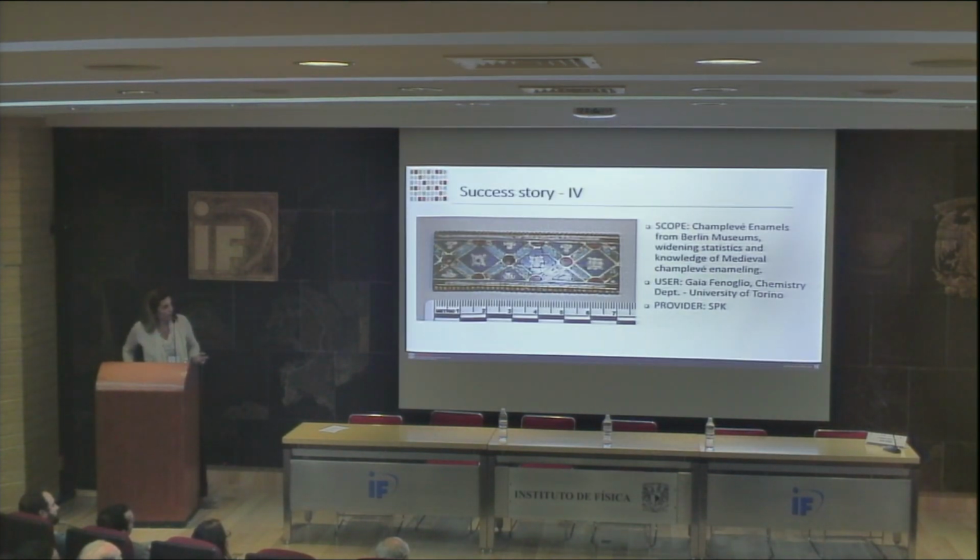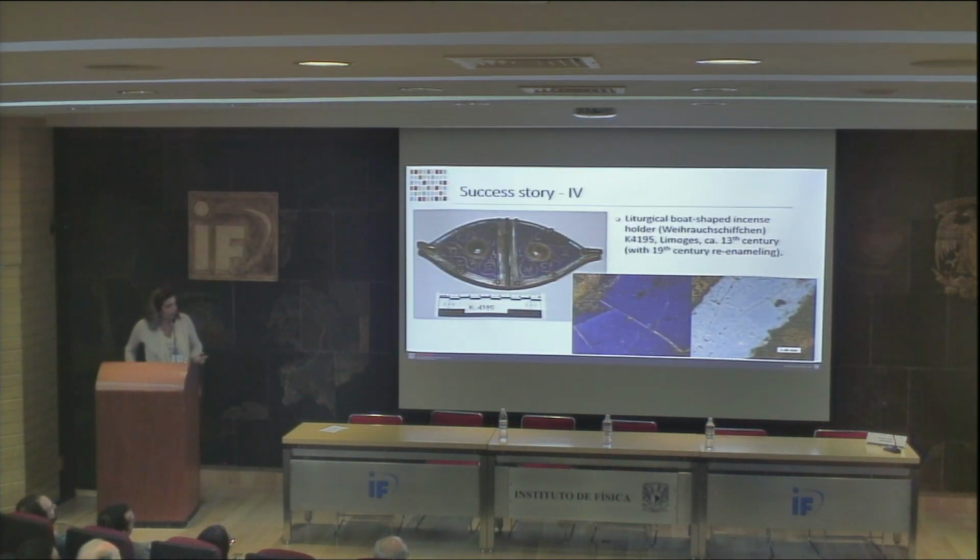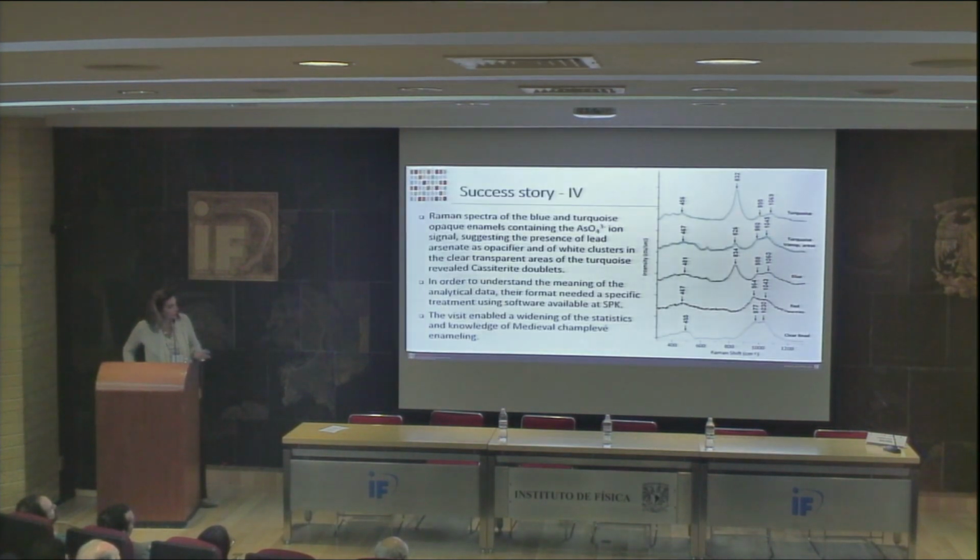Another success story with the scope of studying the Champlevé enamels from Berlin museums. The provider was SPK. This is an example of a liturgical incense holder of the 13th century, and a microscope image showing the blue parts that were studied and analyzed, and these are the intensity spectra, Raman spectra, that allowed us to study the different materials used.